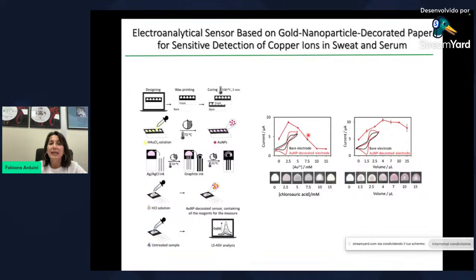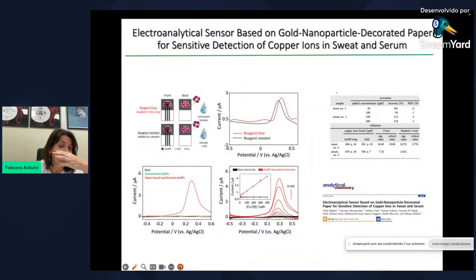And we demonstrate this in the case of copper detection in sweat and serum by using gold nanoparticle decorated paper. Indeed, we can see that with the paper in optimized conditions of volume and concentration of the precursor, we can see the pink color due to gold nanoparticles synthesized inside the paper network. And this is very important when using filter paper modified with gold nanoparticles, because if you add commercial gold nanoparticle dispersion, we observe no peak. Why? Because there is aggregation of the gold nanoparticles on the filter paper. If we use the decorated paper, we observe the response.